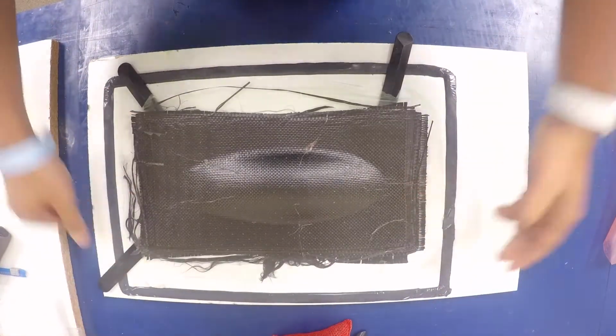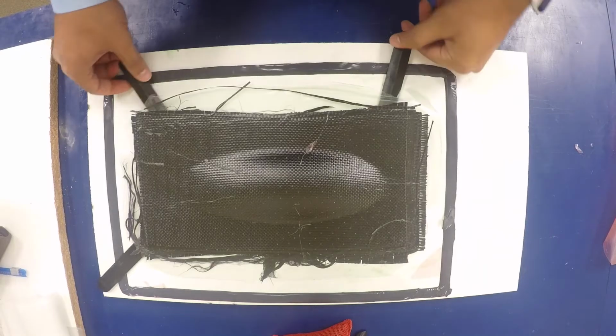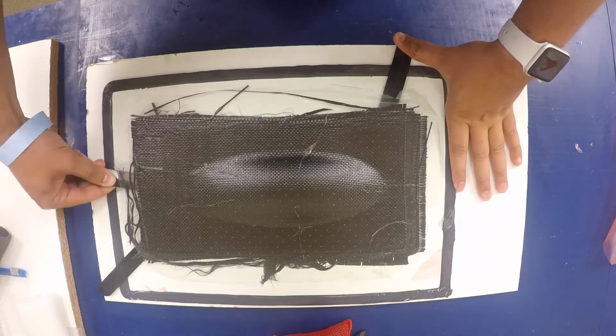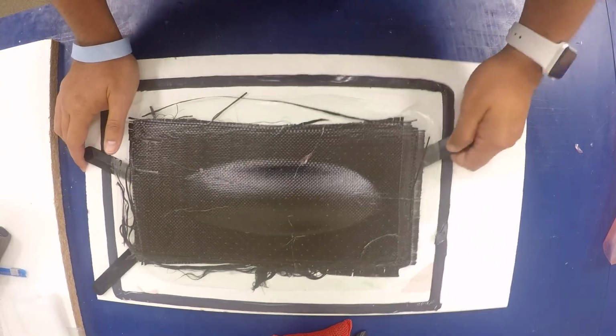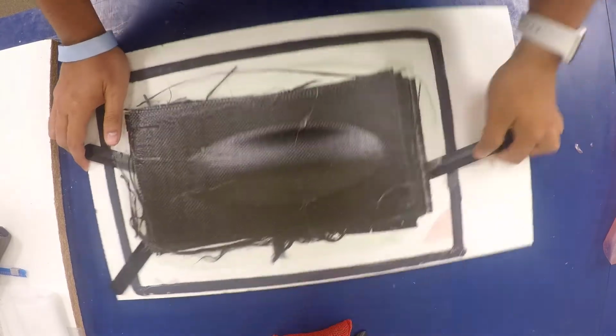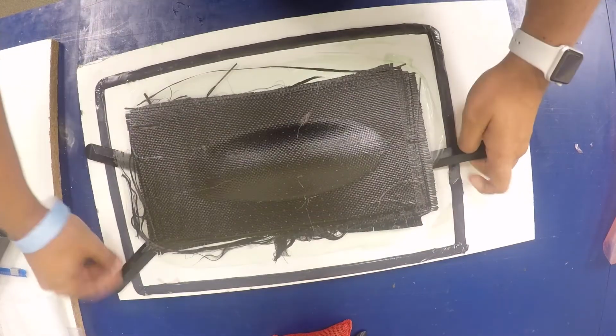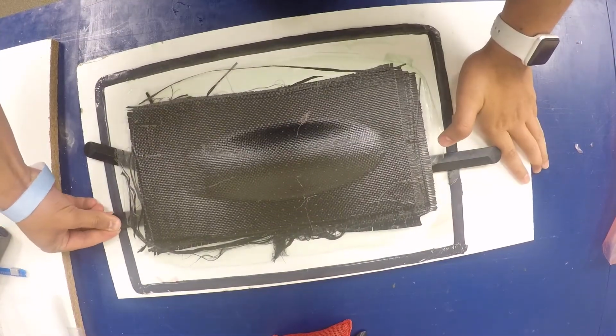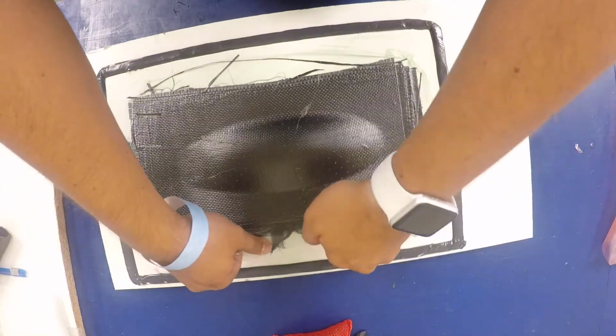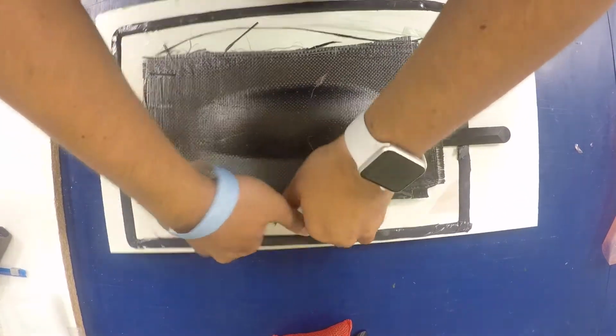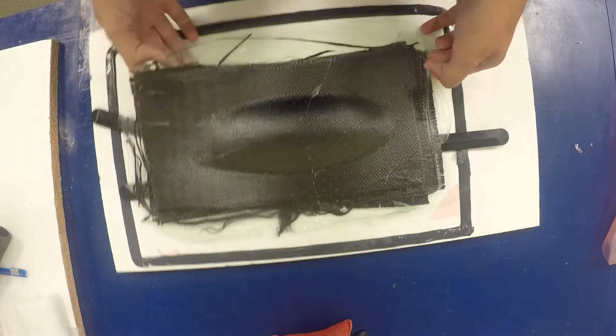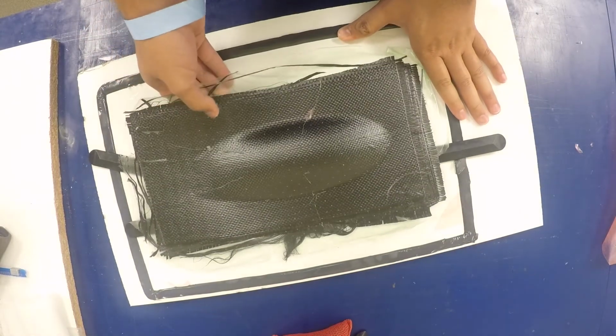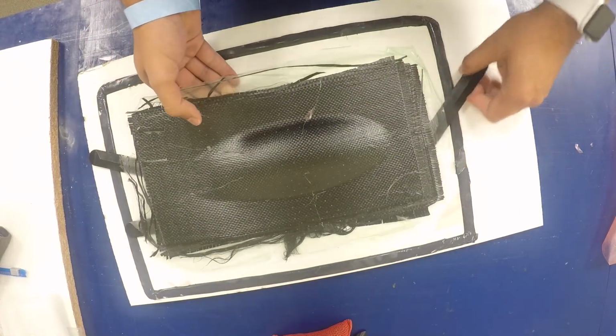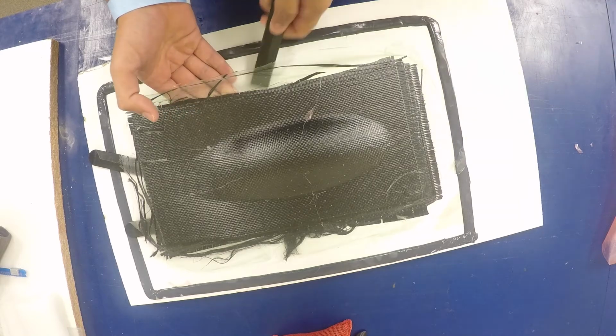During this process, be extra careful with your fingers and your knuckles, as dried carbon can be extremely sharp and will cut through your skin before you realize it. Always pry all of the edges first to debond them from the mold. Just keep working around the mold and attempting to pry it off until it just pops off. Don't use too much force as to break your laminate by bending it too much. At some point, the part will just simply pop off.